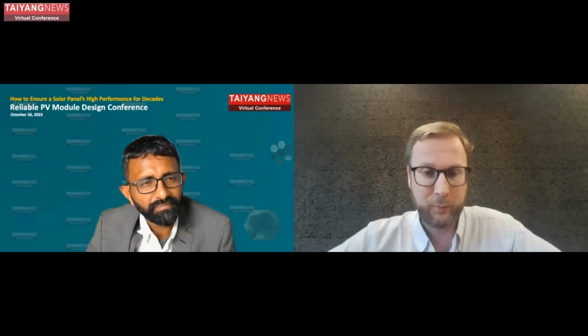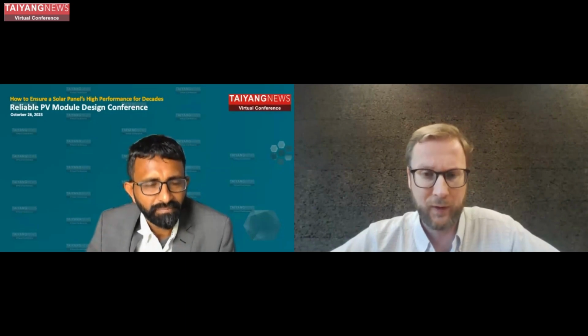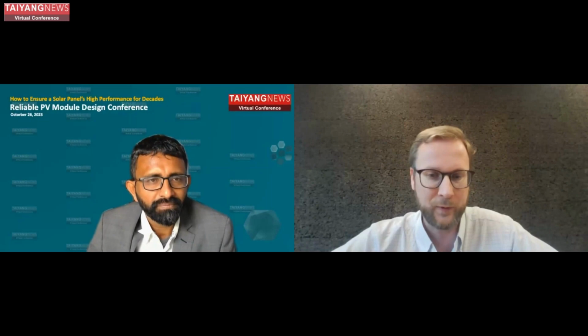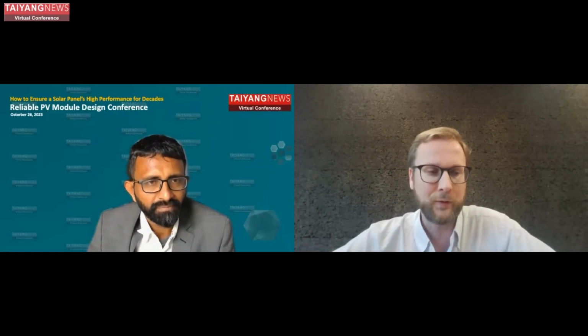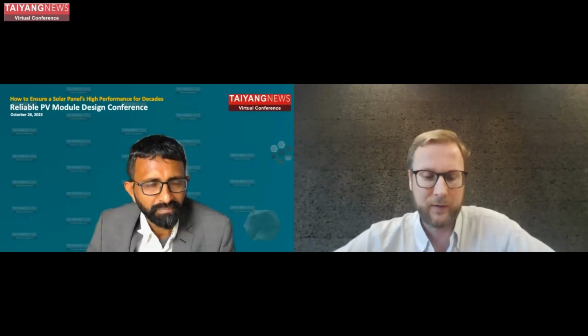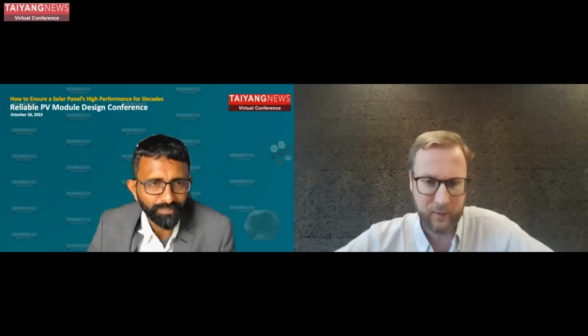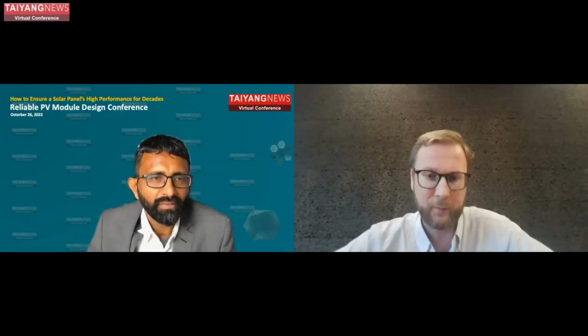Well, to be honest, the bifaciality is a little bit less than compared to a PERC module, because for a PERC module, you can also optimize very strongly on the back. That is also what you need to do there to still gain efficiency, because there's nothing left almost where you can improve. But for the IBC cells, it is much more important to do front-side optimization. So there is some bifaciality there. I don't think I can disclose yet what the numbers are, but it is a bit more modest than the PERC product.